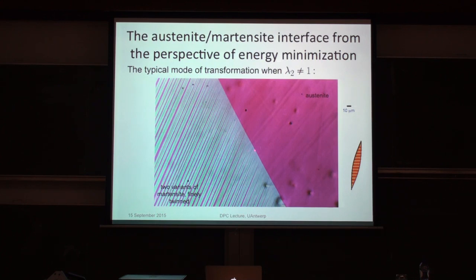So now, if you measure the normal to that interface, of course, to measure the normal, you have to look at it on two different surfaces, but you can do that, and you can measure in three dimensions the normal to that interface. And you express the normal in the cubic basis, the crystallographic basis of the austenite. Now, everybody would have believed that the components of that normal would be small integers. That's a rational plane. They would think that this was crystallographic, so it should be rational. When they measured it, it wasn't. So this plane has somehow nothing to do with the crystallography. It does have something to do with it, but it's certainly not directly related to the crystallography of the material.